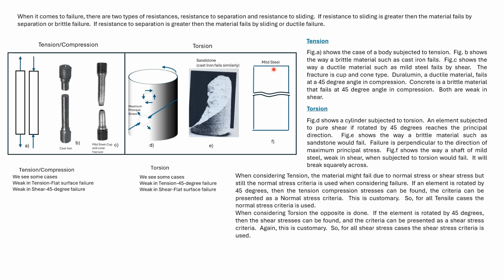Consider a cylinder of mild steel subjected to torsion. Then the fracture is along a flat surface and is due to shear. So we see the opposite cases. In tension, if an object is weak in the normal stress direction, then the fracture is flat. If it is weak in shear, then the fracture is at a 45 degree angle. In torsion, if the weakness is along the principal stress direction, then the fracture is at a 45 degree angle. If the weakness is in shear, then the fracture is in the flat surface.